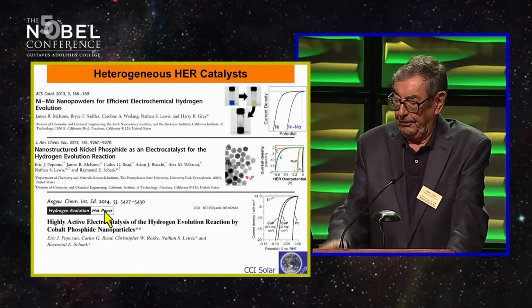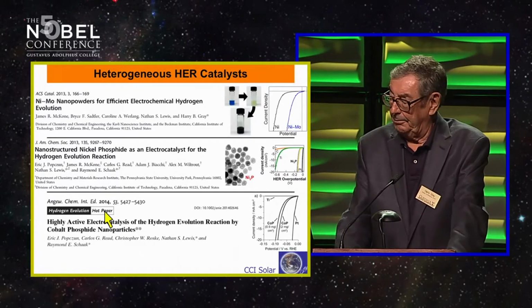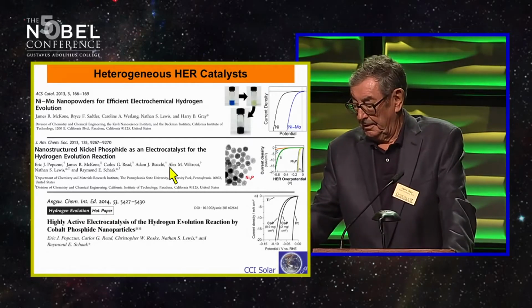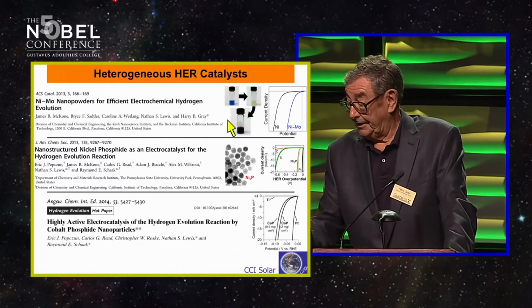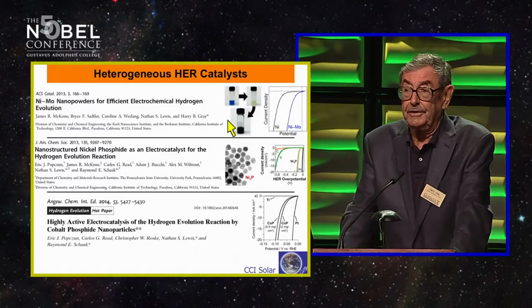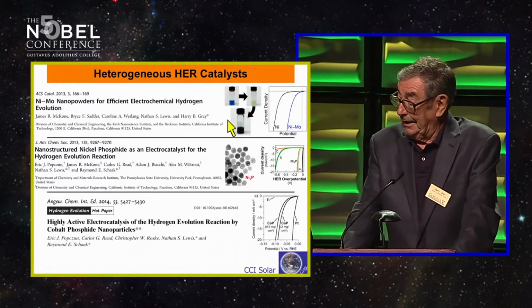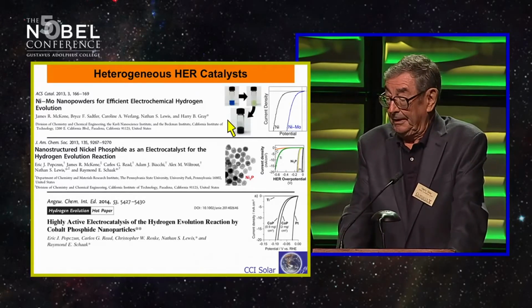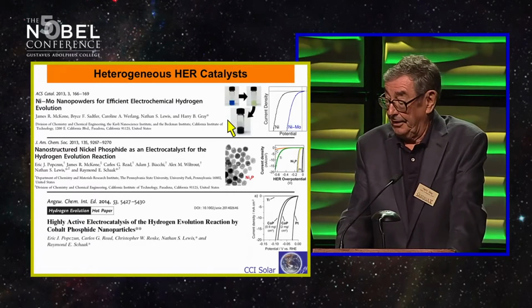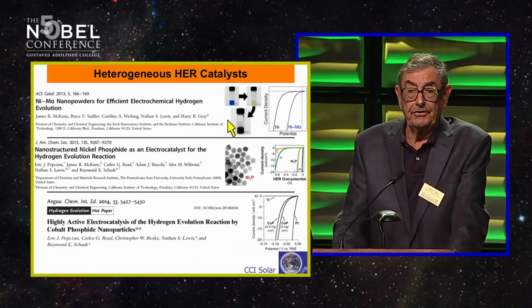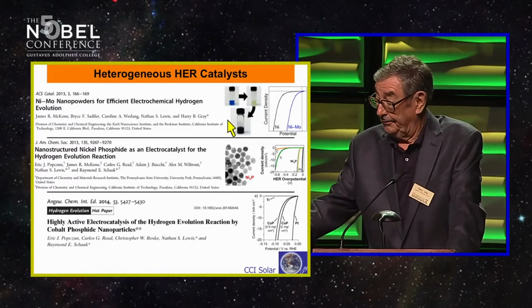The first one was a nickel molybdenum nanopowder, shown here, that can be made by reduction of nickel-amine and molybdate in solution. It's very, very active for hydrogen evolution, and it's very stable. You can run for hours.